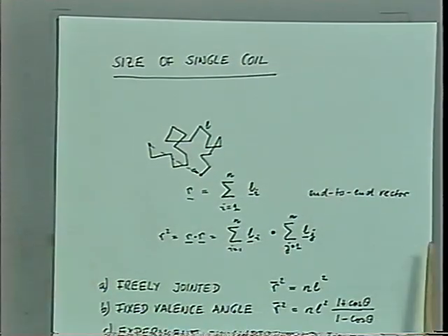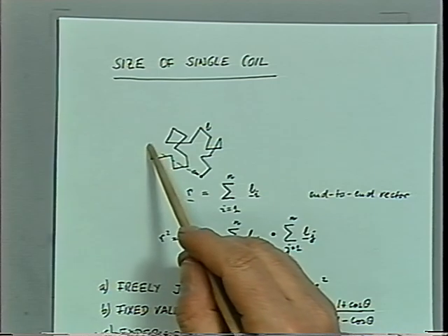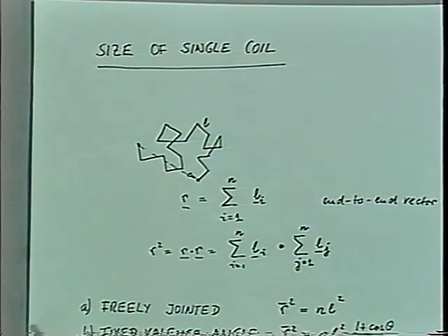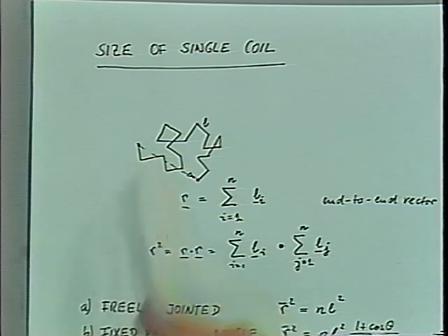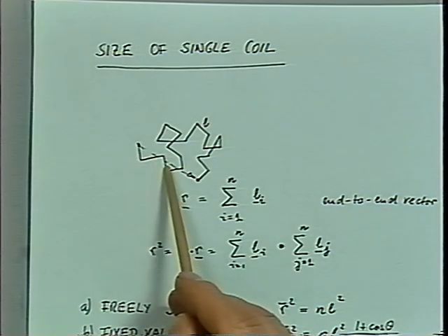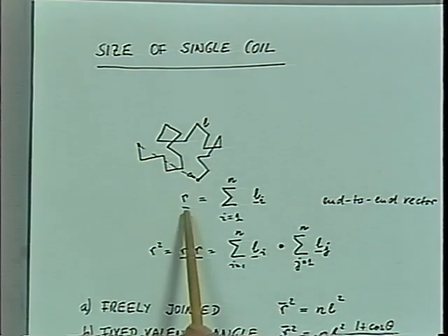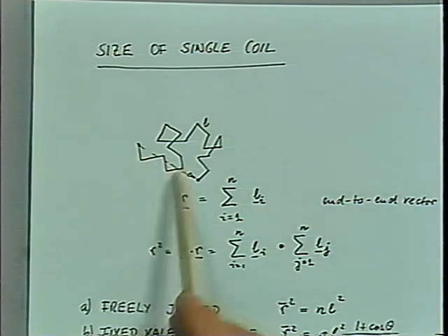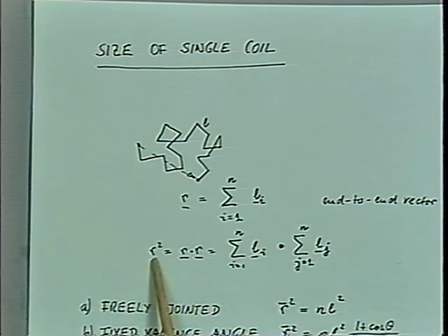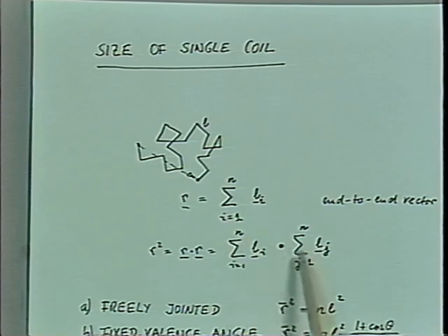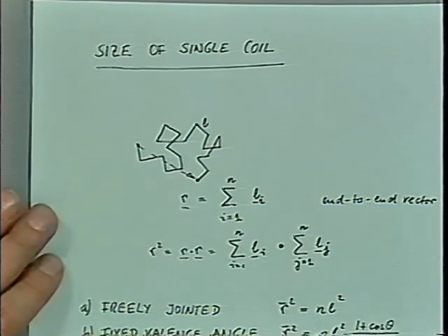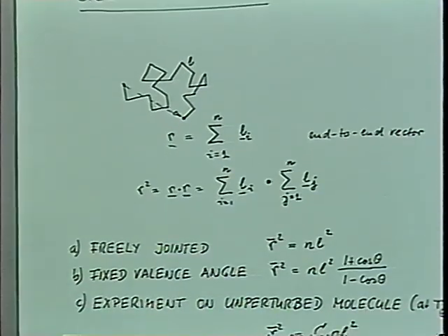That's a very important issue in polymer solution, because the quality of the solvent determines the size of the chain. So if you describe the chain by a random walk, where the molecular chain would be described by a sequence of steps of length L and random direction, every step has a new direction. We could add all those little vectors and get the end-to-end vector from the beginning to the end. This end-to-end vector is given as the sum of all the individual steps. And the magnitude of this end-to-end vector is just r dotted into itself, this times that.